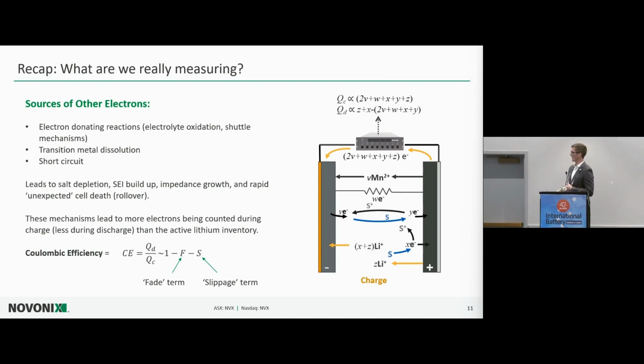Great paper by Jeff Dahn's lab looking at PET tape and shuttle mechanisms that happen there. They actually detected these using UHPC. And then irreversible electrolyte oxidation. And so as we're charging our cell, we're counting all of those electrons. We also have all this other contribution if we can measure it. And that's what UHPC is really here to do, is help identify these things that are happening typically below the noise value in other cycling equipment.